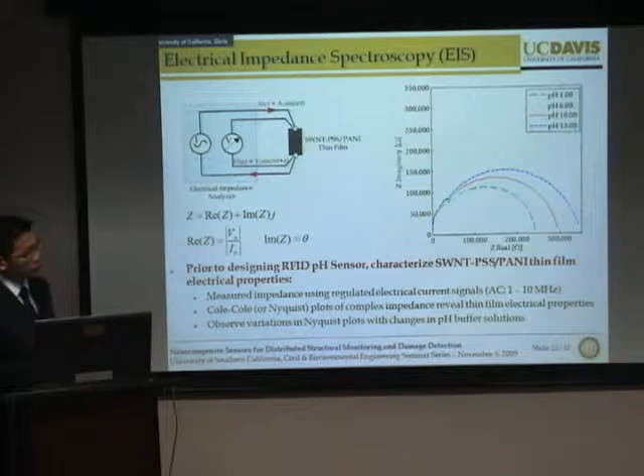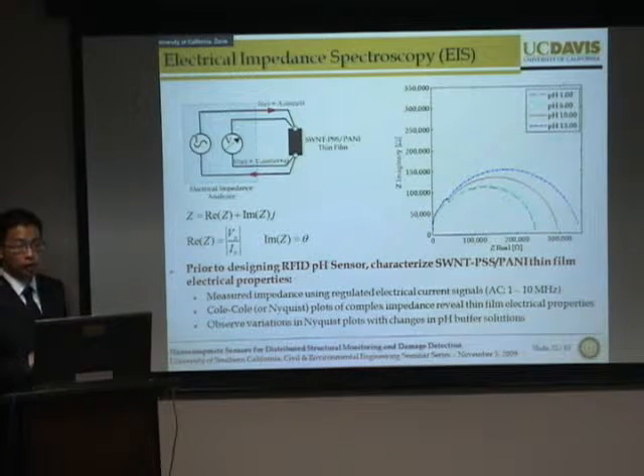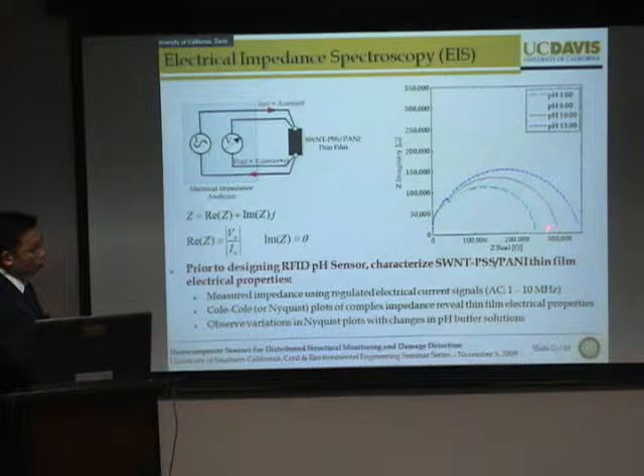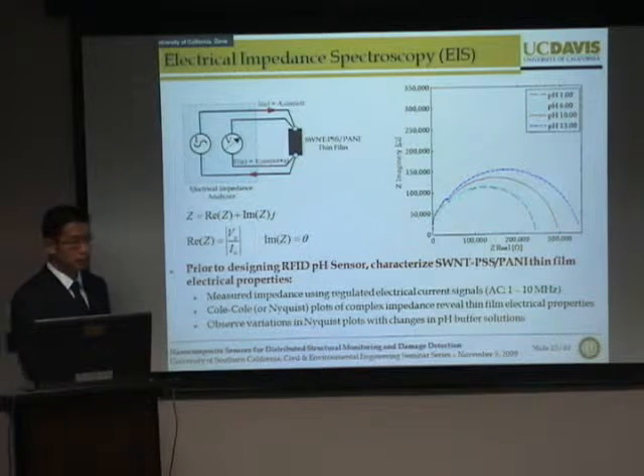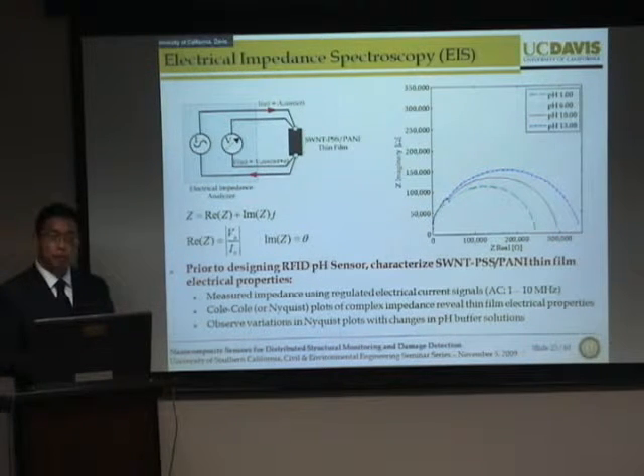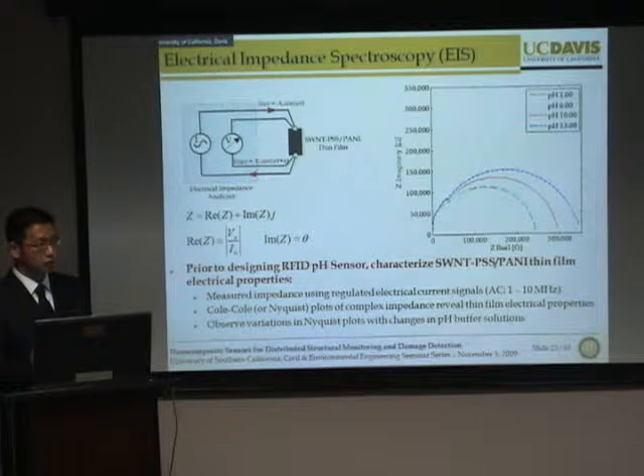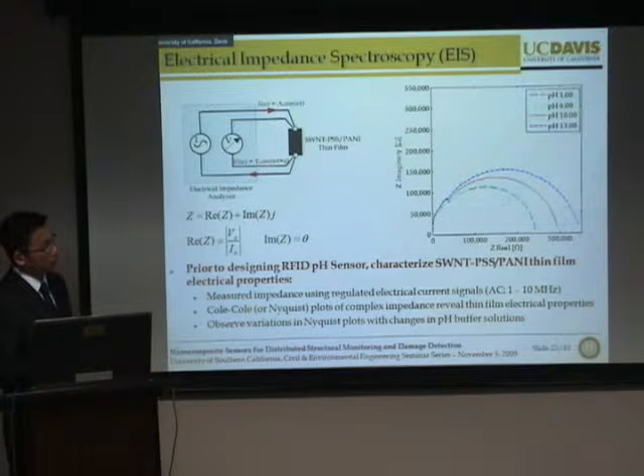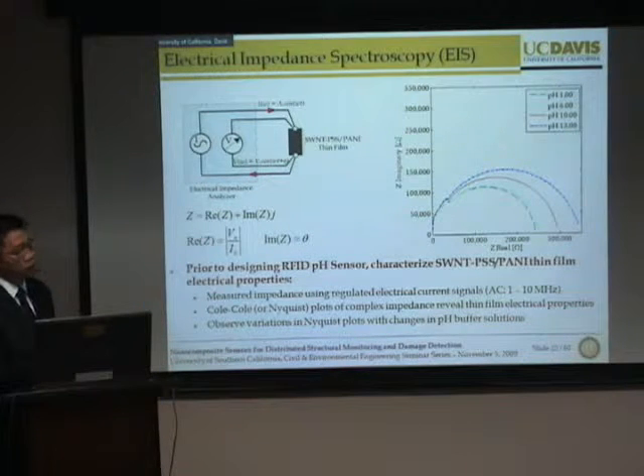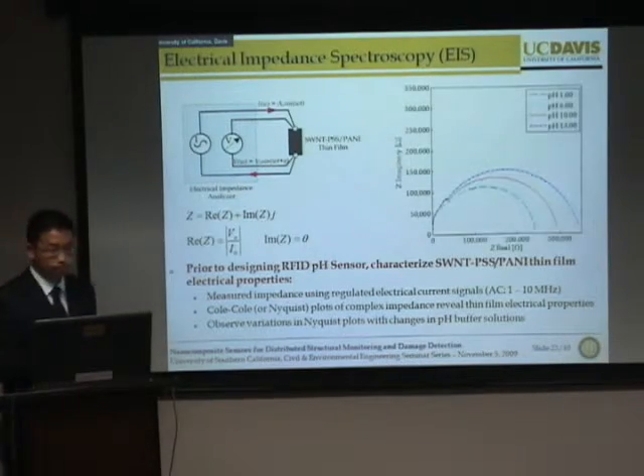Now, if we look more closely at the data, one of the first observations that we can make is that we can observe a semicircular response in the complex impedance domain. And this semicircular response suggests that this thin film behaves as a resistor, capacitor, parallel circuit, which allows us to model the behavior of this material. Now, what's more important is as we increase pH from pH 1 to pH 13, we see an increase in the radius of this circle, as well as a movement of the hypothetical center of the circle.